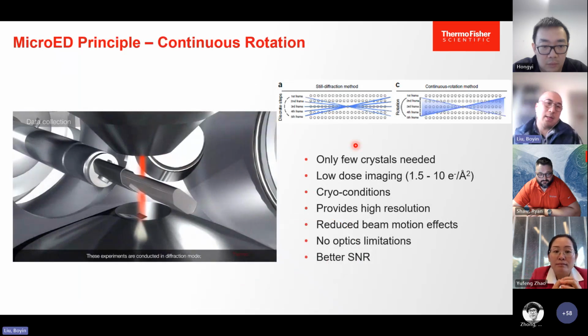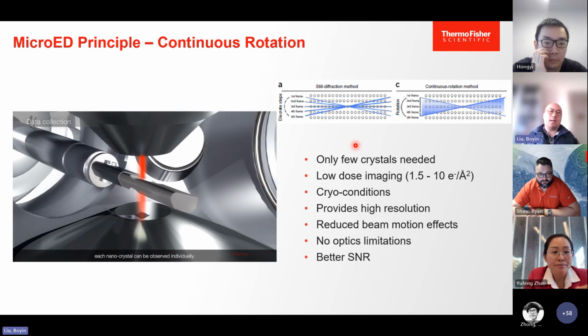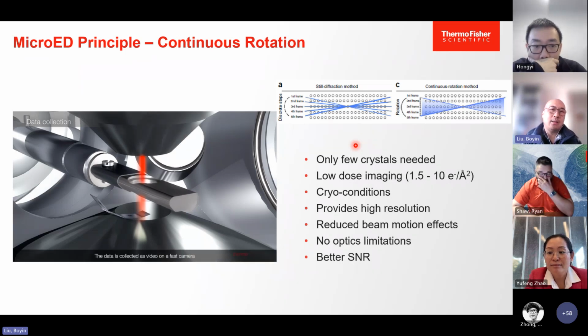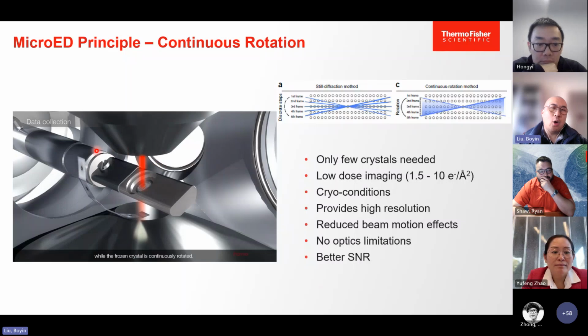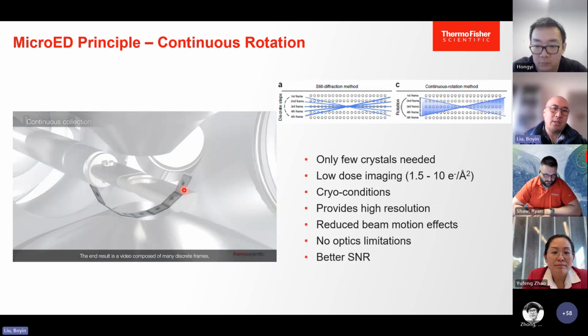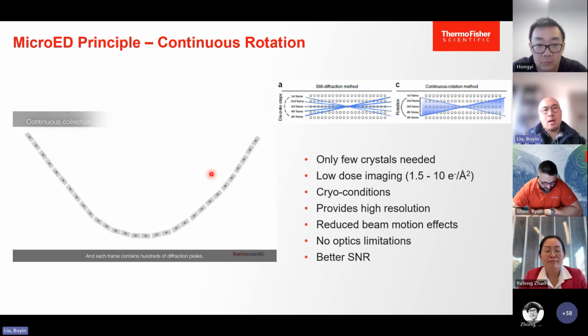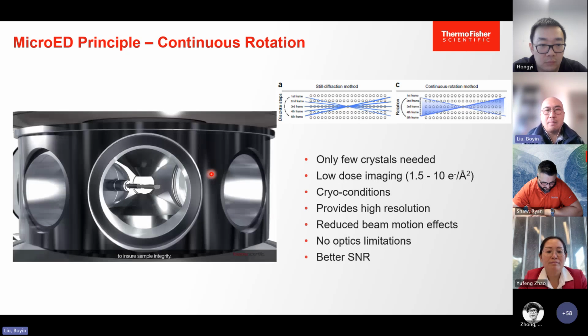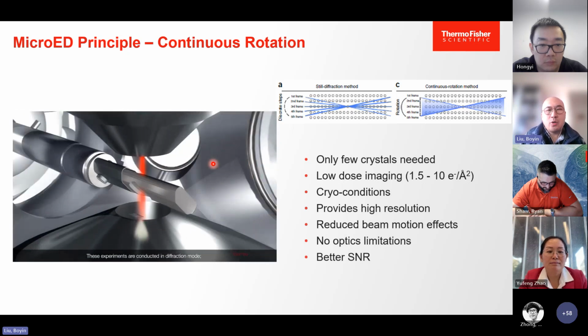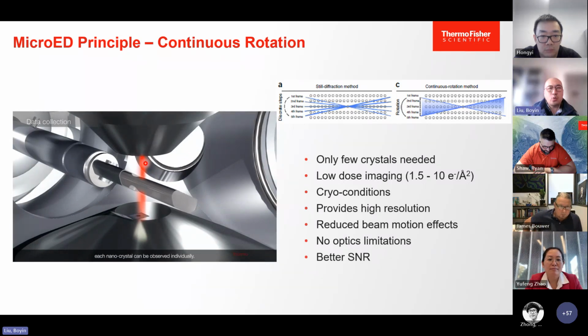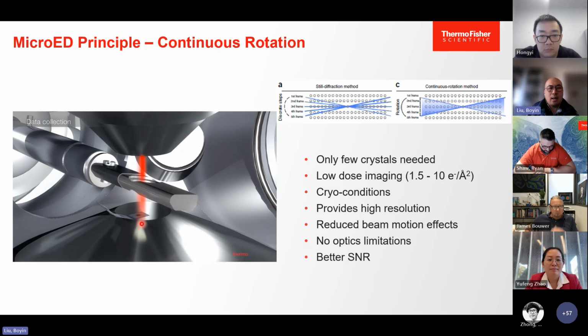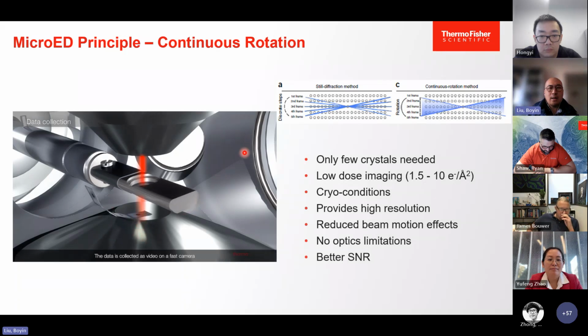Now let's talk about some data collection. As Hongye already mentioned, in MicroED data collection, the sample holder is doing continuous rotation. It's not like tomography where you tilt, stop, image, tilt, stop, image. It's a continuous rotation. The holder backlash is minimized. And then you use a faster camera to do a continuous exposure, and you get a series of diffraction images.